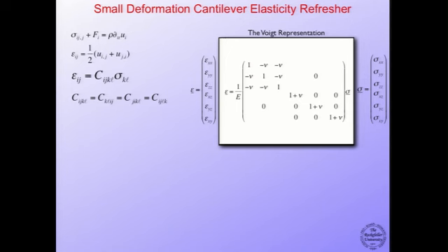However, that's not necessary. As it turns out, even though the material is fundamentally anisotropic along a uniaxial direction, you can model them with isotropic elasticity without really losing any of the understanding of the effects. And so you can pass over to just the purely isotropic compliance tensor. You have a Young's modulus along the primary stress directions, and you get a Poisson ratio elsewhere.